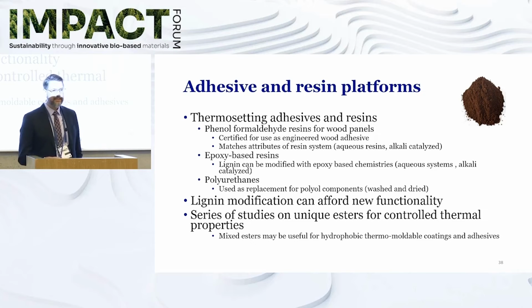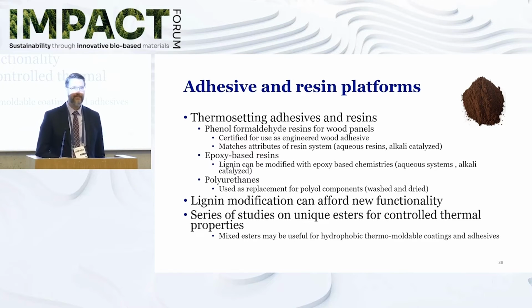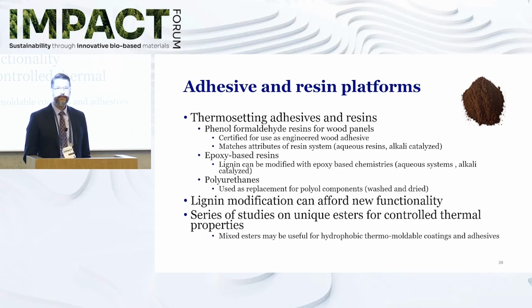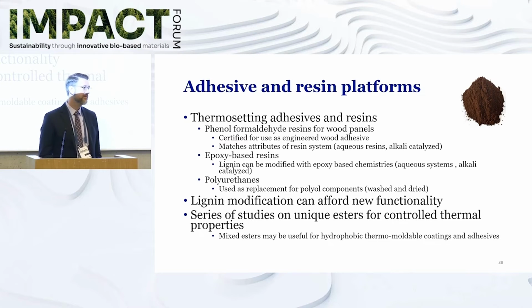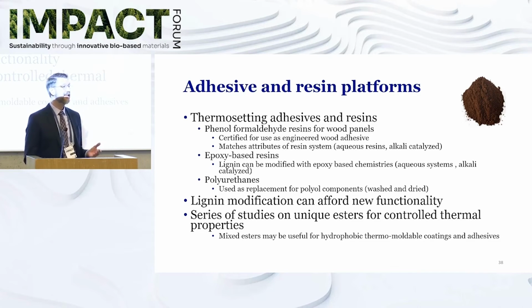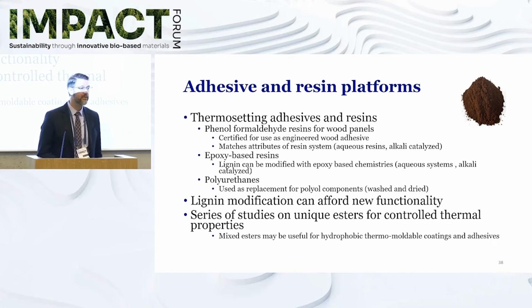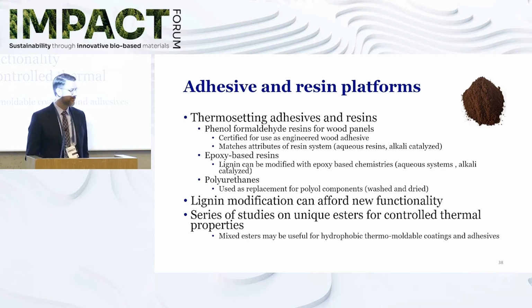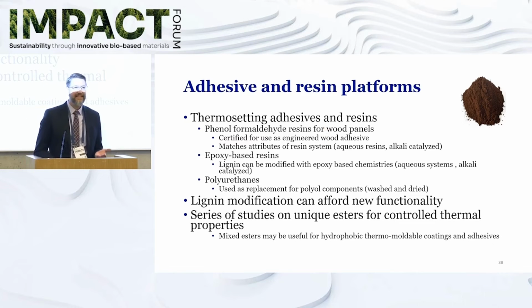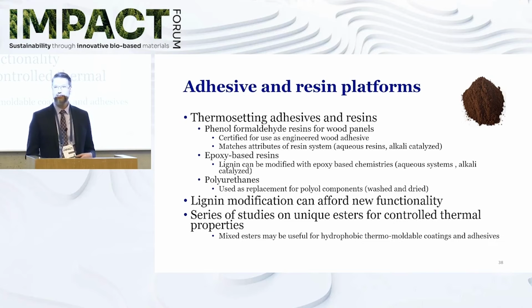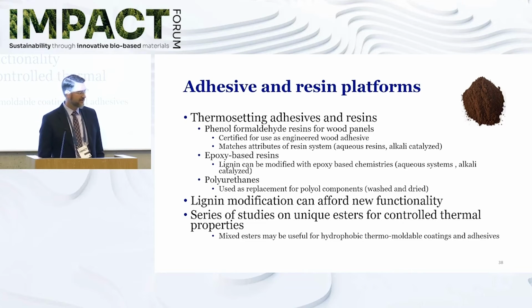Really the market price for lignin, after talking to a couple of folks in the Canadian forest industries, is really around the substitution of lignin into phenol-formaldehyde adhesives. And so lignin has been validated to be used in phenol-formaldehyde adhesives. And so that's adhesives typically when you make plywood, and as well as anything like oriented strand board, things such as that. This is great because actually the PF adhesive technology, it uses an aqueous system, it uses a base catalyzed type of catalyst, and so the lignin attributes actually match this in many cases.